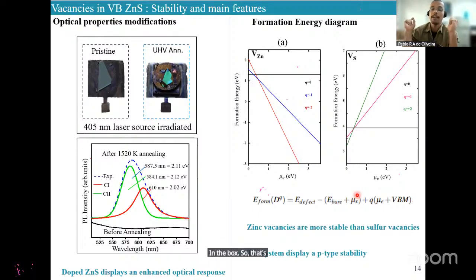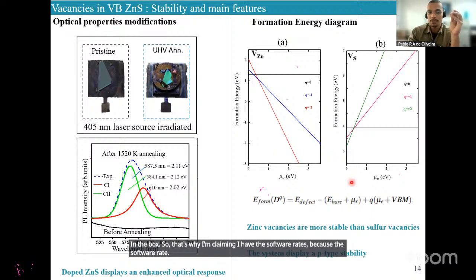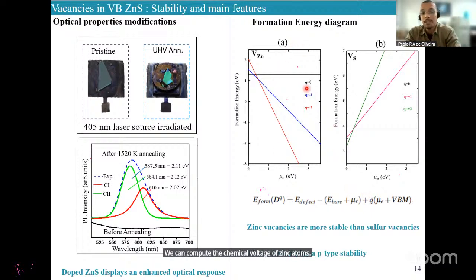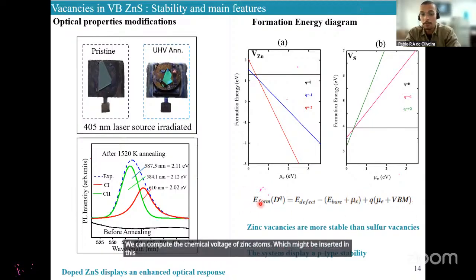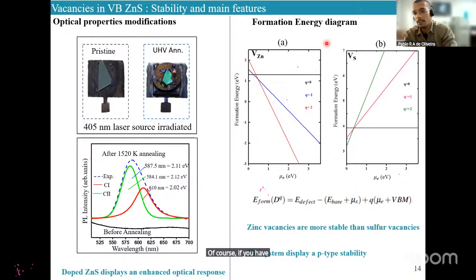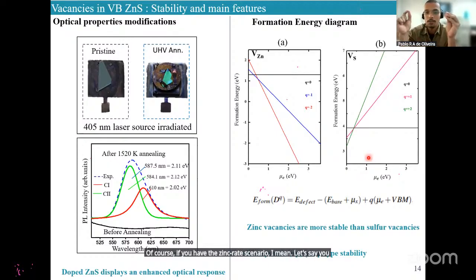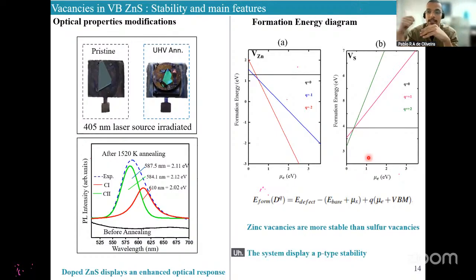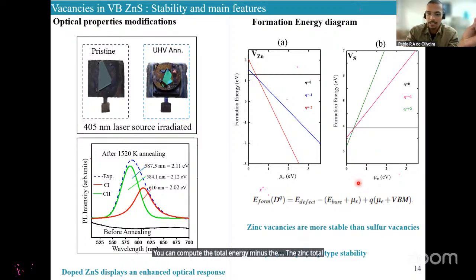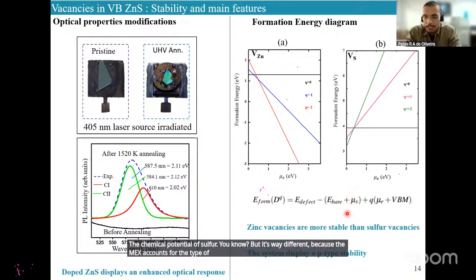So that's why I'm claiming I have the sulfur-rich case, because in the sulfur-rich case we can compute the chemical potential of zinc atoms, which is inserted in this equation to obtain the formation energy. So all these parameters take into account this scenario. Of course, if you have the zinc-rich scenario, let's say you put the zinc atom in a cubic box, and assume you don't have other sulfur around, you can compute the total energy minus the zinc total energy, and then you get the chemical potential of sulfur, you know. But it's way different because the μx accounts for the type of material that is taken out.